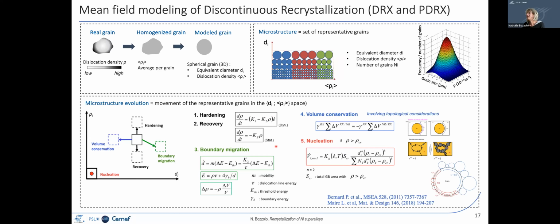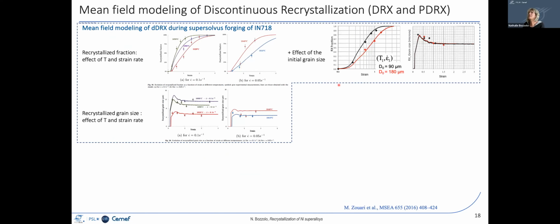So by combining all these equations, you can make the microstructure evolve, and then you can indeed retrieve quite a good description of the evolution of the recrystallized fraction with strain, the recrystallized grain size. Also, you can account for the effect of initial grain size.